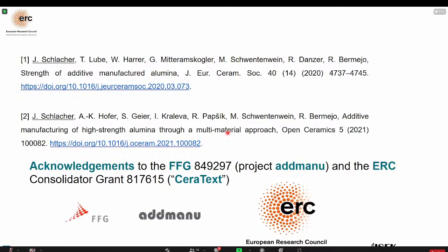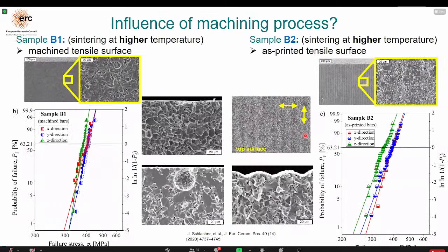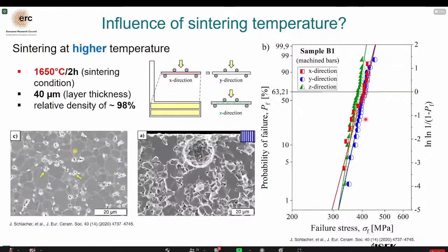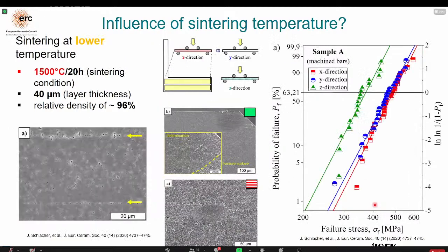This study with lower and higher sintering temperature was used on purpose for this study. Actually, the 1600 or 1650 sintering temperature is used. Maybe a comment from my side: usually the problem with the higher sintering temperature is that you have grain growth, right? Right, that's correct. The grains become too large. We saw it also in the strength distribution that for the higher sintering temperature it is a little bit lower, at 400 megapascals, and for the lower temperature in the good printing directions it is almost 500 megapascals.